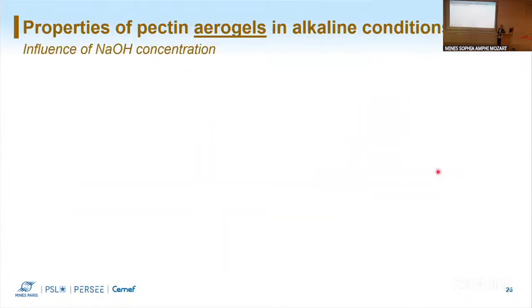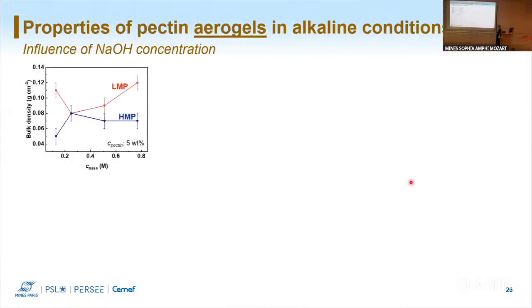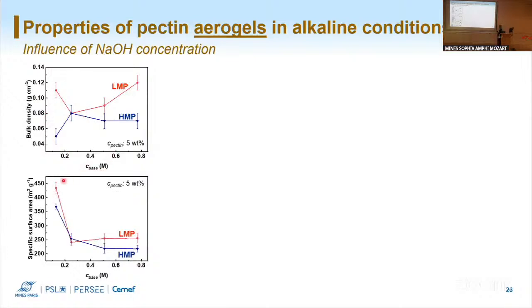So first, we see the properties of the aerogels. Some examples are here. So in red on top, there is low methoxypectin, LMP, and blue high methoxypectin, HMP. And we see that there is not a real trend. The densities are relatively close to each other. They're in low levels. Then for the specific surface area of our materials, we see that when we add a small amount of base, so we are close to neutral pH values, then we have a very high specific surface area, and the properties of our materials are very close to the ones obtained in acidic conditions. Then when we start to add more base, we go to alkaline pHs, and we see a huge drop in specific surface area. And after a point, we don't really see a big difference inside the experimental error.